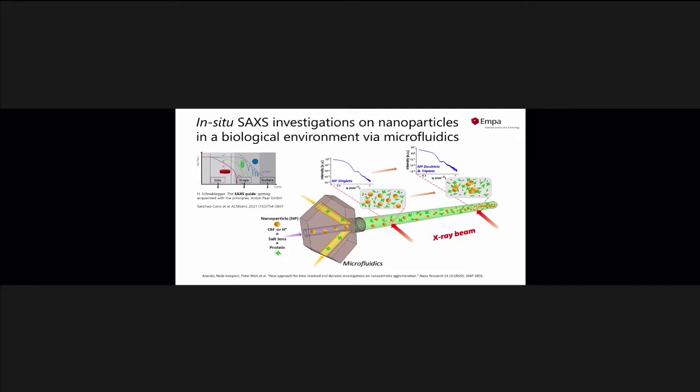This will be mixed here, and then in this capillary, which has a flow of a few microliters per minute, we can dissociate these early events by analyzing with the X-ray beam early in this mixing device or late in this capillary, and we can dissociate the early fraction and later fraction very nicely. We did the analysis at different positions on this capillary, and by that we could learn what happens over time.